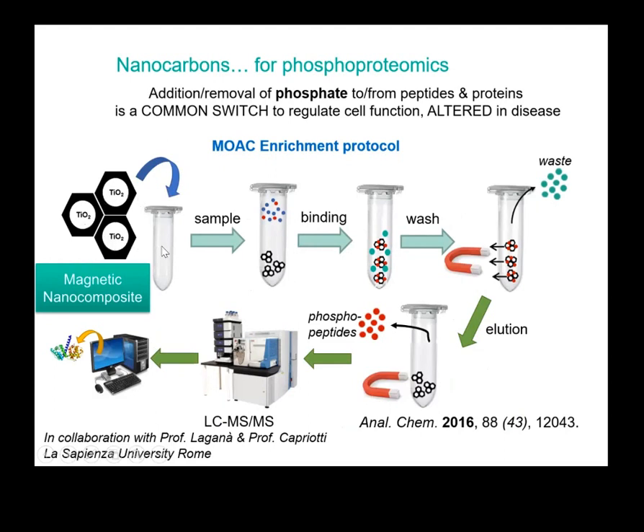In the first example, we used graphitized carbon black, which is a relatively popular scaffold in analytical chemistry, or at least it's gaining more attention. It's widely available and relatively low cost. And so here, the way it works is that if you have a magnetized nanocomposite, then it can be very handy for magnetic separation. And therefore, if you have a biological sample, you can load materials on the nanocomposite and separate the waste through magnetic separation. And then, for instance, by changing pH, you can elute the bound biomolecules or biomarkers from the nanocomposite.